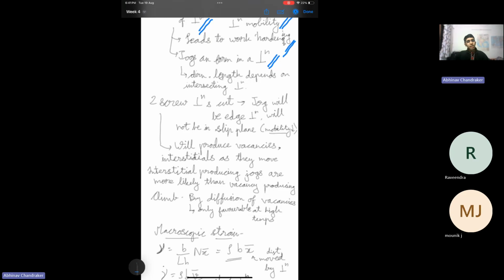Sir has explained in good detail how jogs form and what can be the effects of it. So if you are forming a jog due to two screw dislocations or a screw and an edge dislocation, the resulting jog tends to be mobile. One thing to keep in mind is that when these jogs are forming due to intersection, the jog portion of the dislocation will have a Burgers vector which will remain the same as that of the previous dislocation. The line direction will change depending on the Burgers vector of the incoming dislocation, but the Burgers vector of the jog will remain the same as the one of the original dislocation.